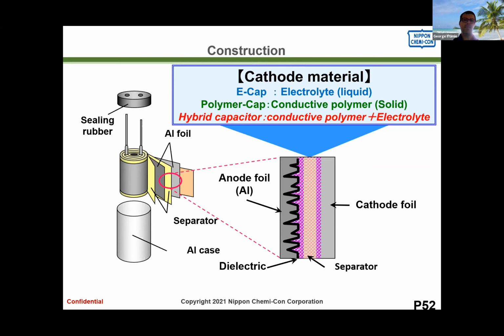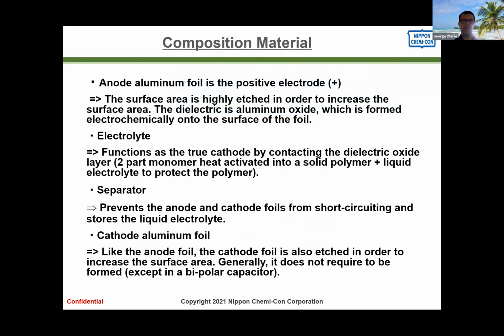So essentially a hybrid is a polymer capacitor where you replace the plastic separator with a paper separator, and you add a little bit of electrolyte in there. And I mentioned earlier, the biggest function for that liquid is to protect the polymer from humidity, basically. This is basically the same. The only difference is the electrolyte.